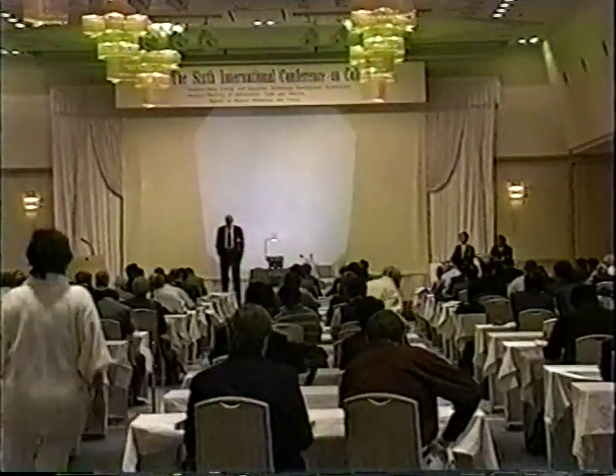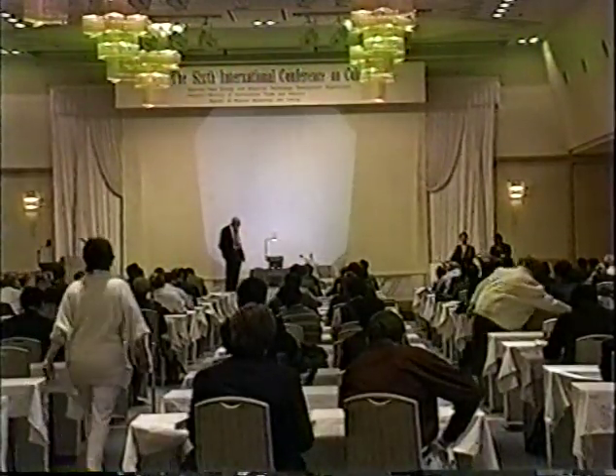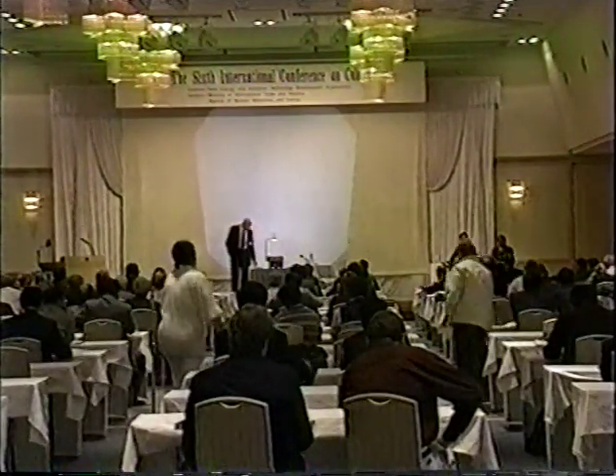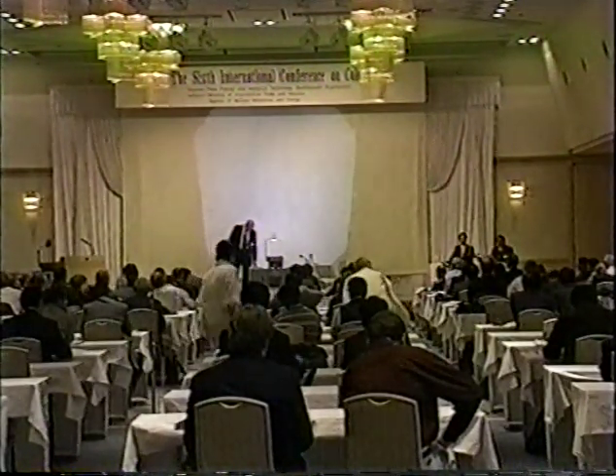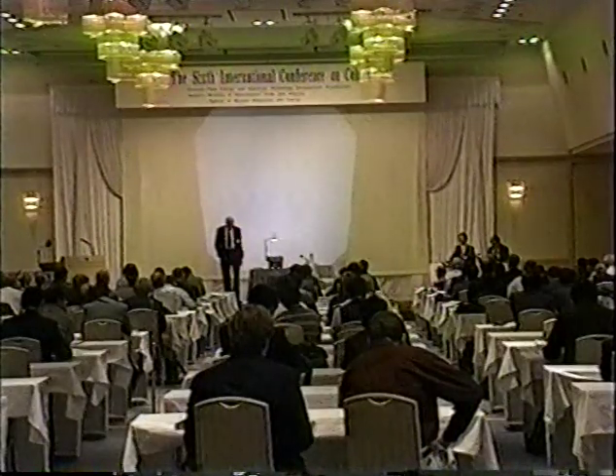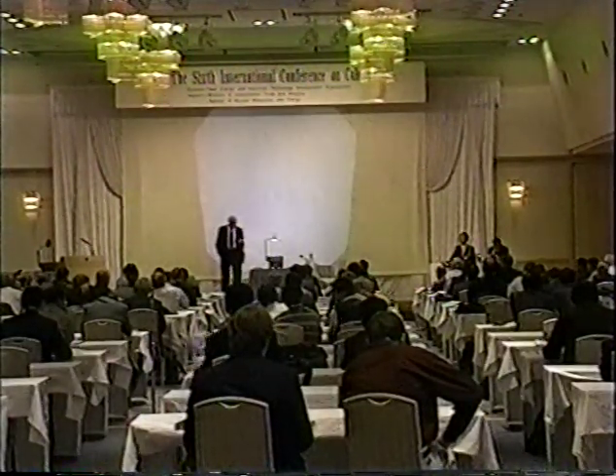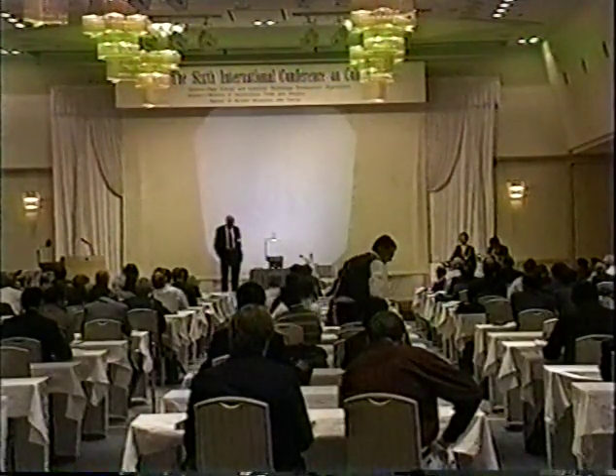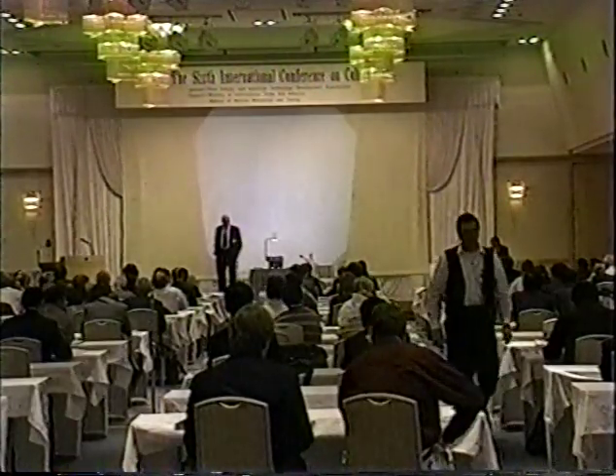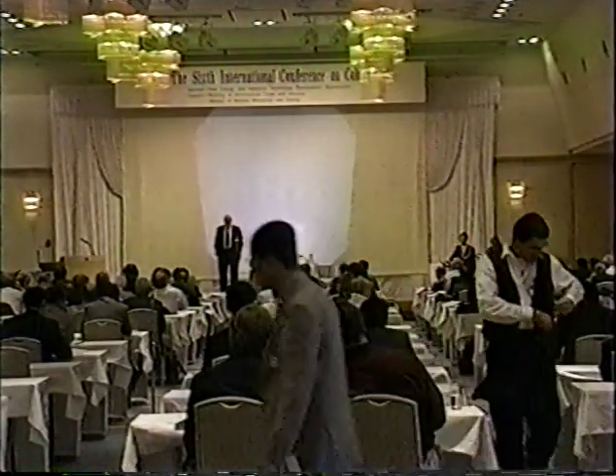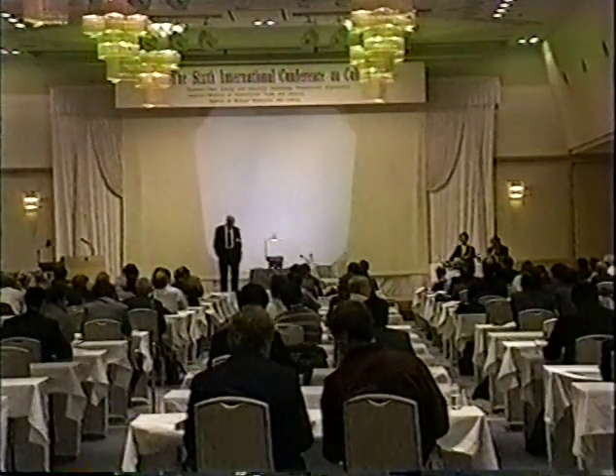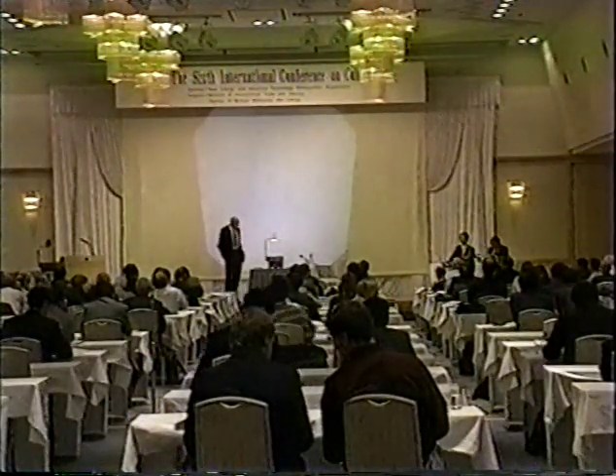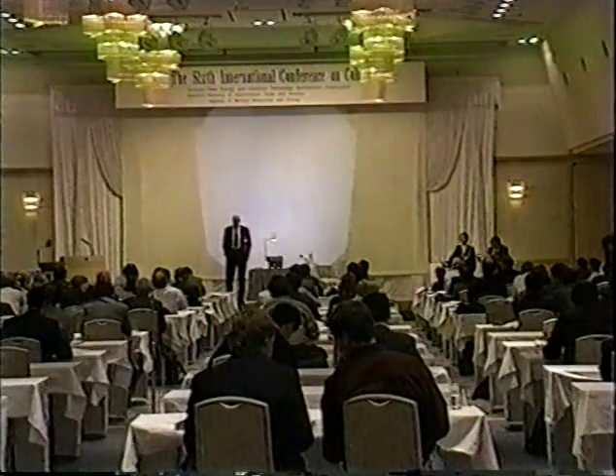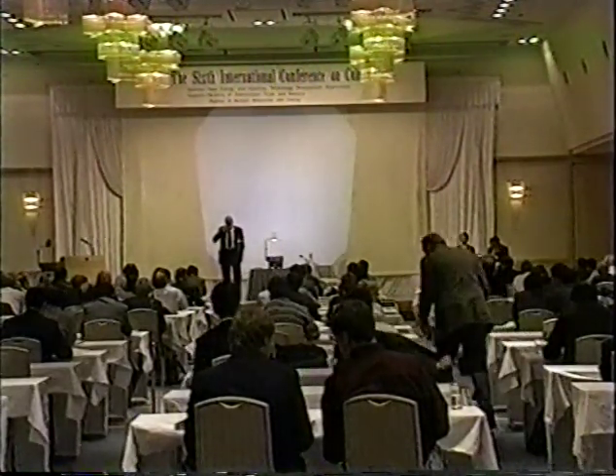I was encouraged to do this one because of Kevin Wolf's results, seeing reactions or apparent reactions at very low levels, but nonetheless fascinating, at deuterons and protons on palladium isotopes. And so I said, well, if Kevin can get the deuteron into the palladium nucleus, I ought to be able to get the deuteron into the boron-10 nucleus at quite a larger rate because of the lower Z.